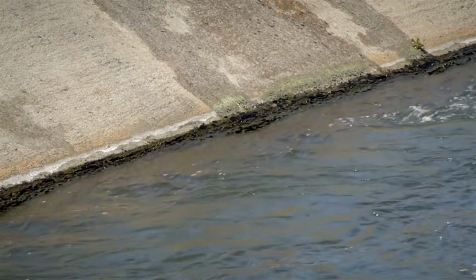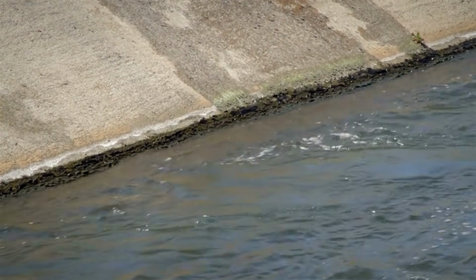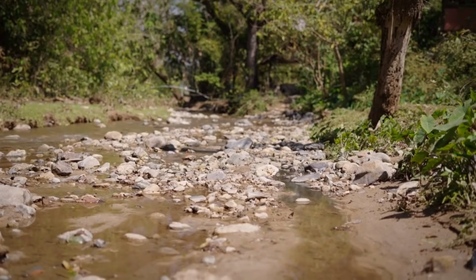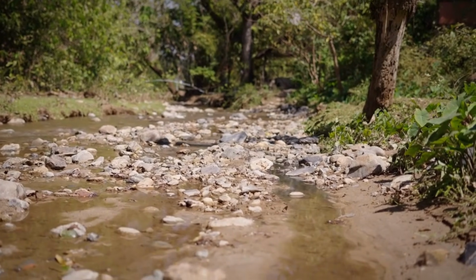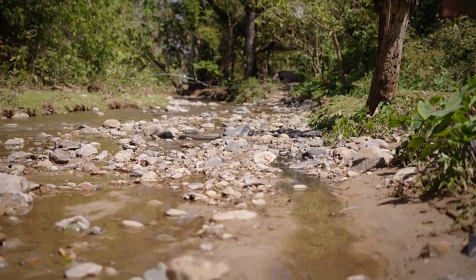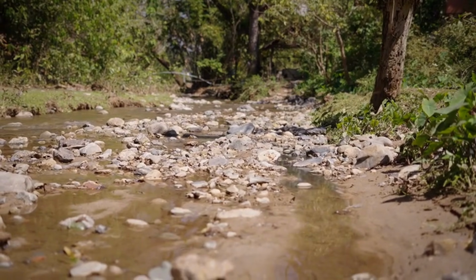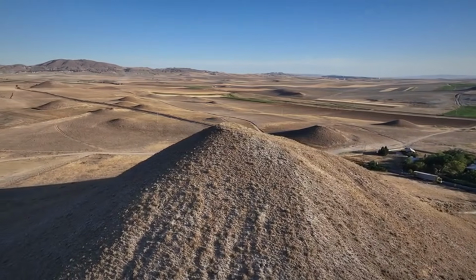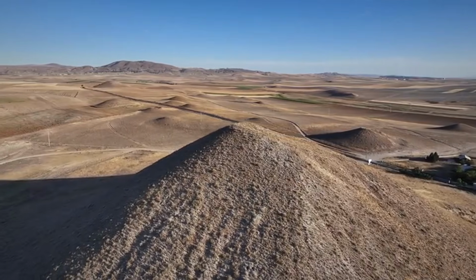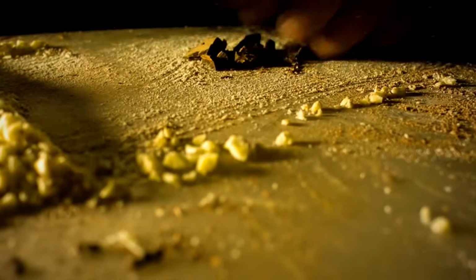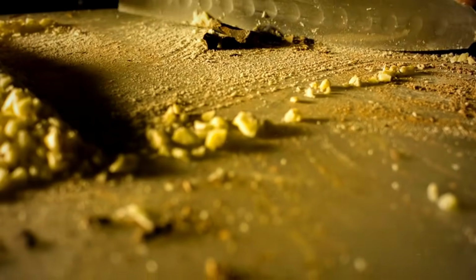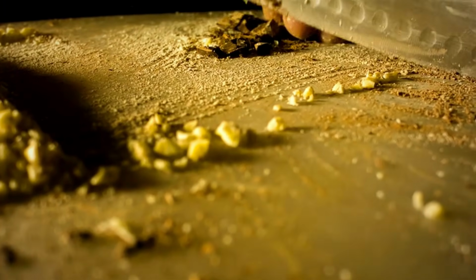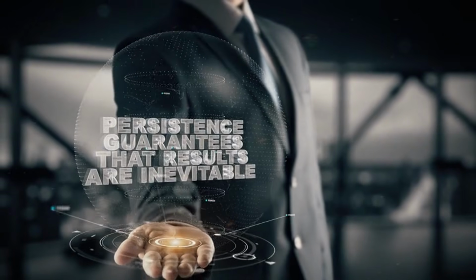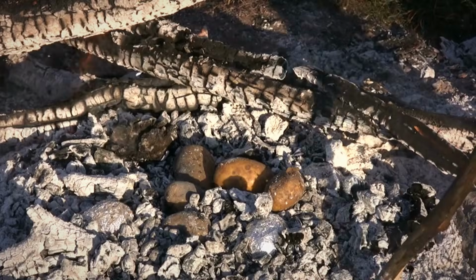A similar logic applies to magnetic separation. Run a magnet over one split of your crushed sample and leave the other untouched. Process both. If recovery improves without magnetic material, you now know your gold is not magnetically associated and may be free milling. If recovery drops, some of your gold may be in magnetic sulfides like pyrite or arsenopyrite, requiring different processing logic. Even visual proof has a role.